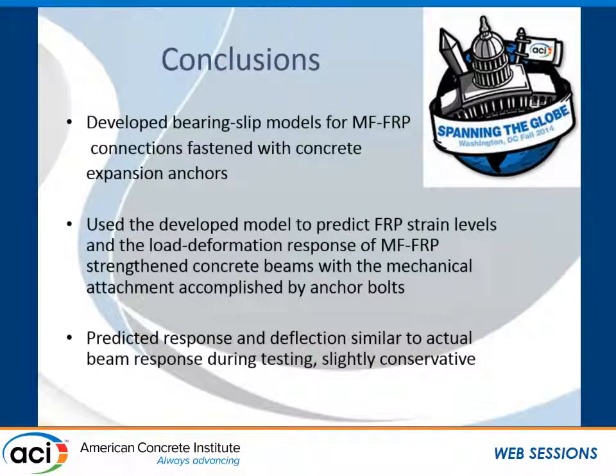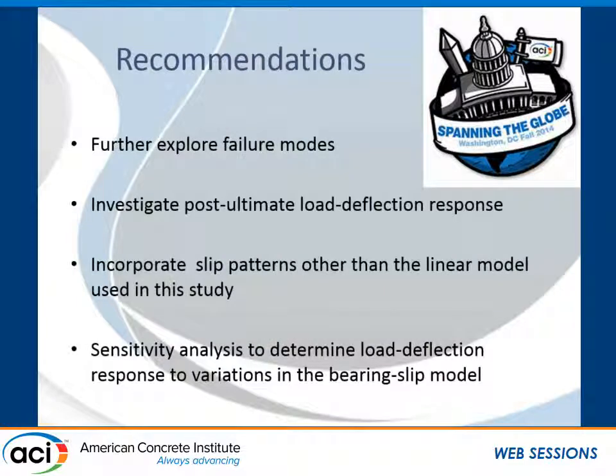So what conclusions have we drawn from the work? Well, first of all, that the proposed bearing slip model accurately predicts the ultimate capacity of a section, and further that the ultimate strength is better predicted for beams in which the failure mode is also correctly identified. Predictions of strain and deflection were also quite reasonable, and the accuracy of those predictions was not dependent on correctly identifying the failure mode. As to recommendations for future work, we need to take a closer look at failure modes and the effect on predicted beam response.